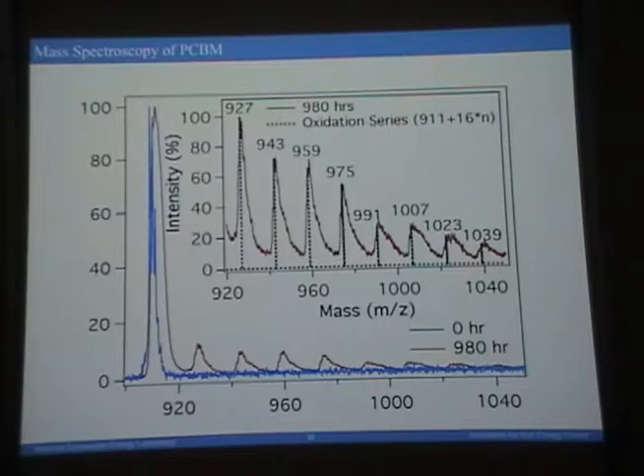Now, the surprising thing to me was, and this is what I'm showing you here, because all I did was throw this up and say it's the PCBM. What I'm showing you here is a mass spectrometry set of data for the material after it's been irradiated. Here's the original PCBM, with one oxygen, two oxygen, three, four, five. It keeps adding singular oxygens.